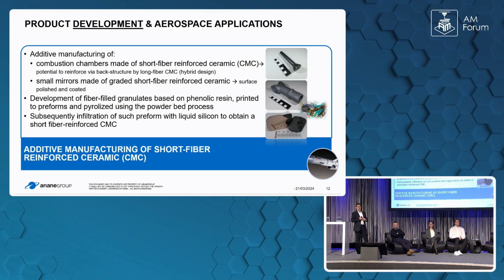If we need higher strength of this kind of material, we can do a reinforcement via back structure by our textile processing. And here we developed, quite similar to the DLR approach, fiber granules based on phenolic resin, printed to preforms, pyrolyzed, and all this was done in the powder bed processing. The last step was then a liquid silicon infiltration to create out of this carbon-carbon material a carbon-SiC material. And as you see, we did nozzle extensions, a kind of combustion chamber, mirrors. That's what we did with this kind of processing.